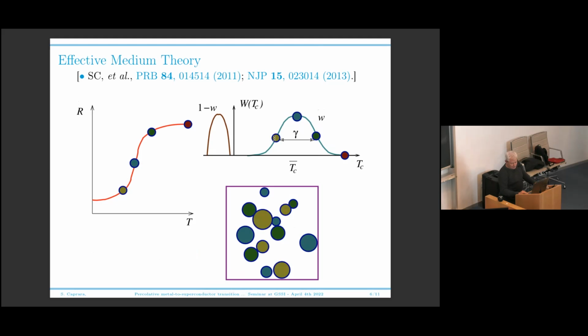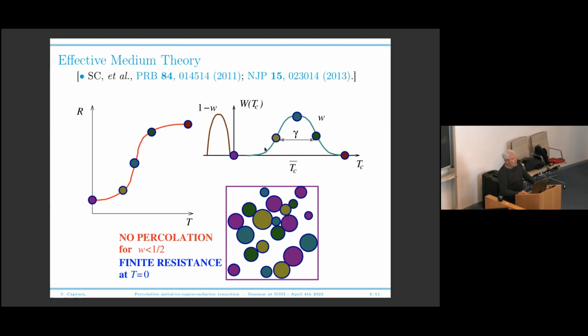Then you go even lower in temperature, and you have other regions that are nucleating and you are down here. Now imagine that when you reach zero temperature, you have nucleated all the regions that could possibly nucleate. If this fraction is less than 1/2 for some reason, 1/2 if you have homogeneously distributed disorder. If you have a spatially correlated disorder, then of course the percolating fraction can be even much less than 1/2. But let's assume, just for the sake of discussion, that we have a completely randomly disordered medium, then the percolation threshold is 1/2. If your total superconducting fraction is less than 1/2, as you see, there is no percolating superconducting path from one end of your system to the other end.